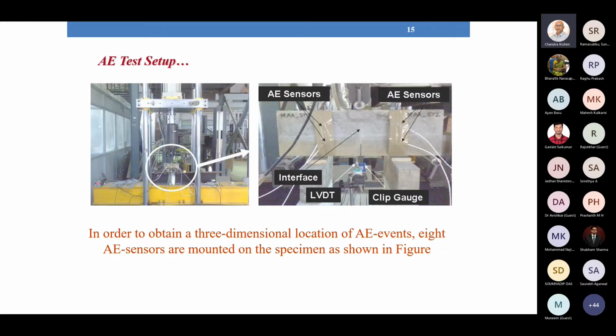This is the typical setup on a servo-controlled machine. The monotonic static tests were performed under crack mouth opening displacement control, CMOD control, of about 0.001 mm per second. That was the rate at which the loading was done. And then we have an LVDT to measure the vertical displacements. Here, these are the acoustic emission sensors. They are protected because once the beam fails, we didn't want to damage them. You can see in the slide.